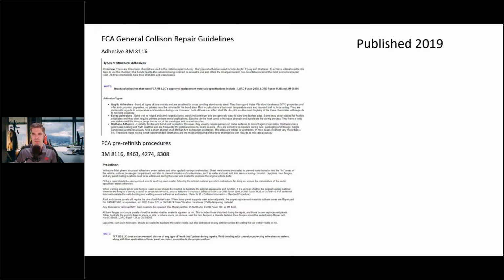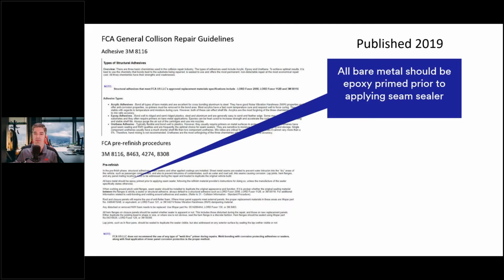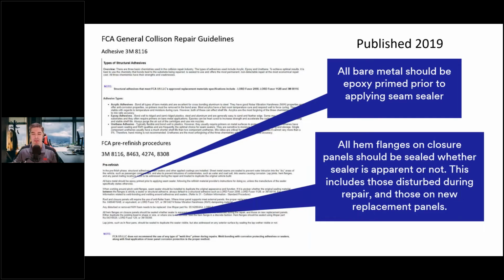Coming back to FCA, so they also have refinish repair guidelines. So this is like the bottom half here. I'm going to highlight the pre-refinish guidelines for repair, and they go on to say that all bare metal should be epoxy primed prior to applying seam sealer. All hem flanges and closure panels should be seam sealed, whether seam sealer is apparent or not. This includes those disturbed during the repair and those on new replacement panels.